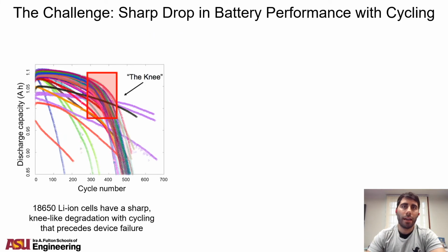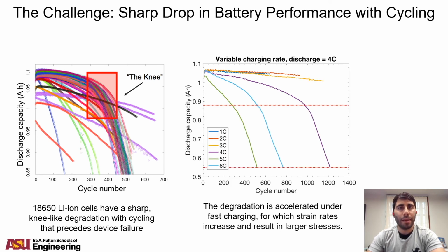On the chemical side, there's been a knee-like degradation mode that's been observed in discharge capacity fall-off for 18650 cells with cycling. And this effect is exacerbated or accelerated under fast charging, upon which there's going to be higher strain rates that develop from the movement of lithium ions. The mechanism is still not fully understood.